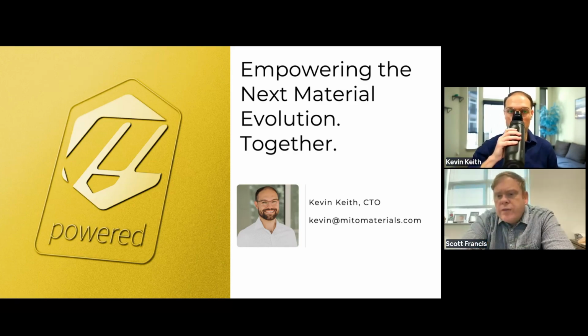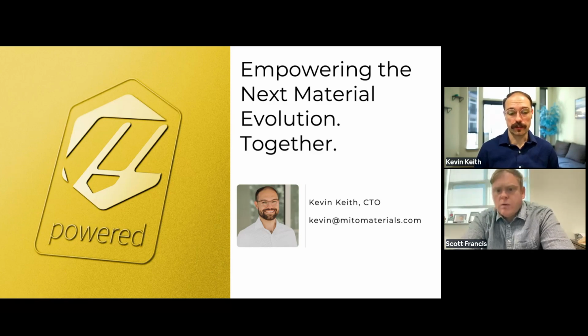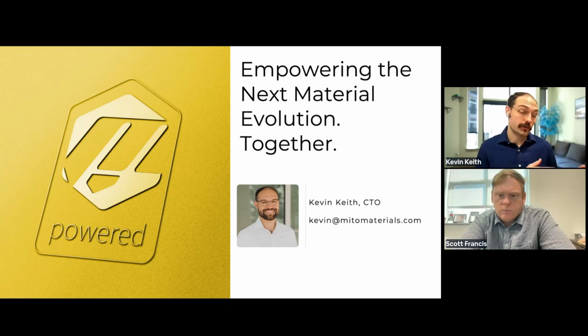Okay. You showed a lot of physical property data. Have you measured any changes in electrical properties? We have a couple of data points in terms of functionalized graphene oxide. When we put this functionalized graphene oxide into a carbon fiber reinforced thermoset epoxy, it's a 50-50 ratio between epoxy and carbon fiber. We load that functionalized graphene oxide into the resin at 0.1% by weight concentration, and it actually increases electrical insulation anywhere between 200 and 400%. That's because of the chemistries we tie onto the graphene oxide.